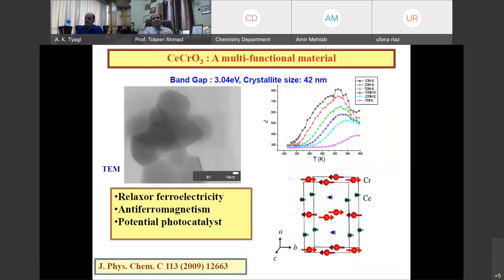So to cut short the story, we made a number of new compounds. I will run through them. We made CeCrO3 almost 12 years back. Time has gone very fast. This compound turned out to be a multifunctional material. It shows relaxor ferroelectric behavior, as you can see from the data of dielectric constant versus temperature. It shows antiferromagnetism as seen by neutron diffraction, and its band gap is 3.04 eV.